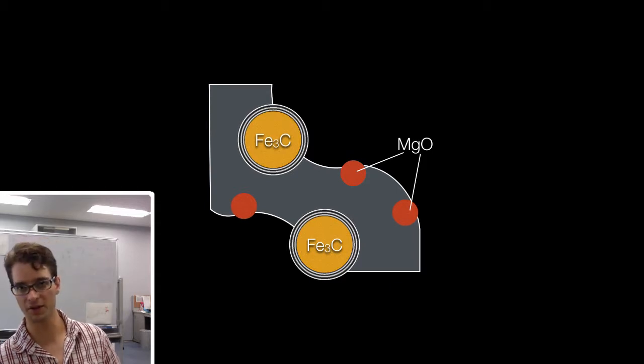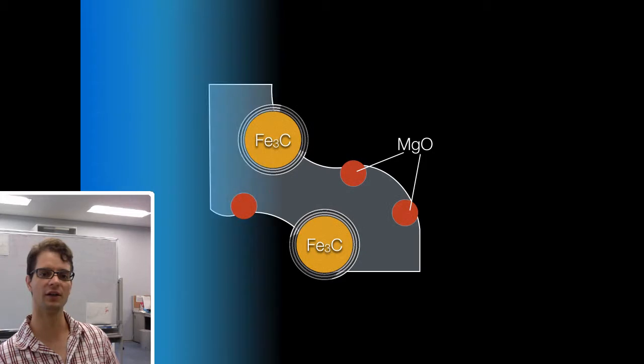Interestingly enough, this is not the catalytically active material. This material becomes really catalytically active when you wash away the metal salts, leaving this very porous structure with the remnants of these graphitic carbon shells.